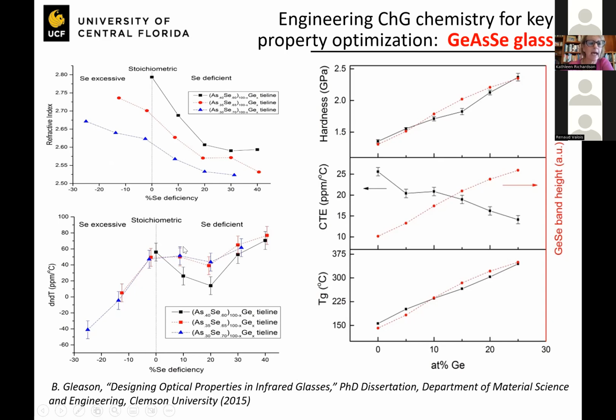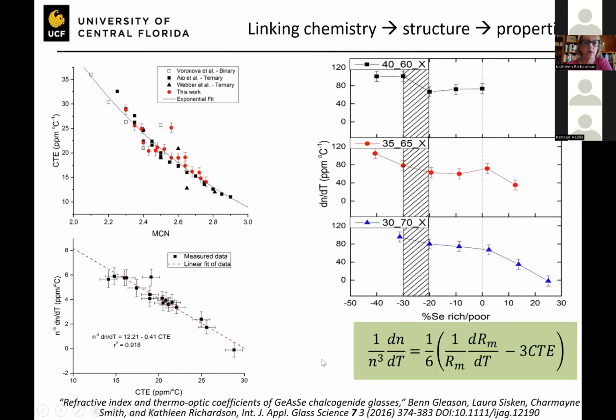Now, while he did this work for this simple germanium arsenic selenide system, what he showed is that we understand very nicely how to go from stoichiometry to either excess or deficient network structures. And so we can change the ingredients, but it gives us some insight in terms of designing these materials for these applications, thinking about not only their optical properties, but these properties which largely dictate the manufacturability. And Ben did a beautiful job of linking the chemistry, the structure, and the properties to allow us to now get into a mode where he showed we could, in a predictive way, engineer our materials to have a characteristic property. In this particular example, he was looking at having a glass that had a dn/dT, or a change in index, close to 0 as a function of about 100°C temperature change.